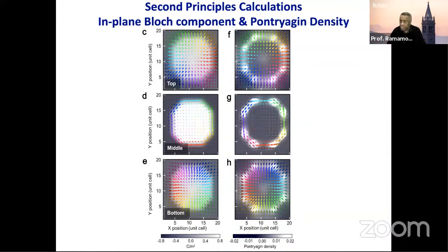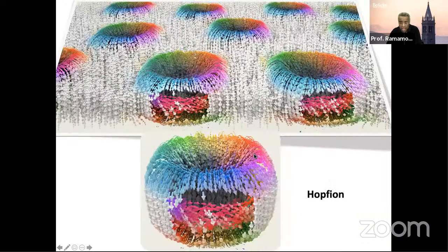But the one thing that we never expected, and again, this is really kind of an unexpected emergent thing, is that in addition to this so-called Neel component, which goes up and down like this, there is a Bloch component. You can see that these arrows are going from right to left. And that Bloch component turns out to be very important. It's exactly like your belt. If you're left-handed like me, I wear my belt from left to right. If you're right-handed, you do the opposite. And therefore, these objects could also be chiral. And indeed, that's what these objects look like.